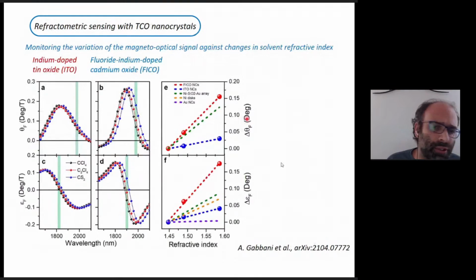Just to conclude, we tried the refractometric sensing experiment with ITO and fluoride indium doped cadmium oxide, another heavily doped semiconductor, and we found a better sensing sensitivity compared to all other magnetoplasmonic systems in the literature today.